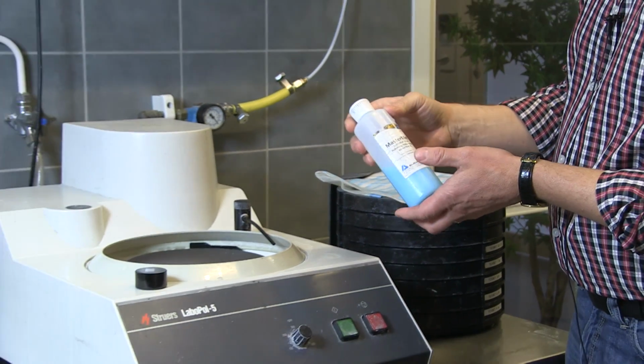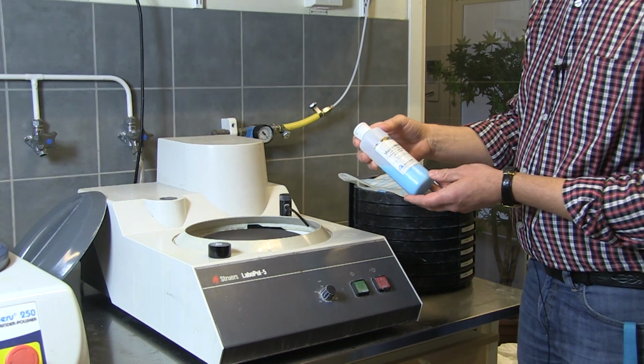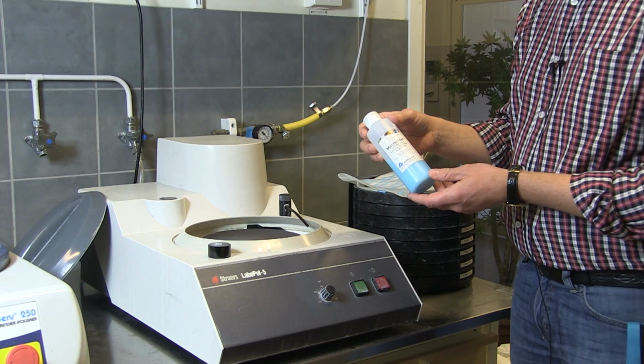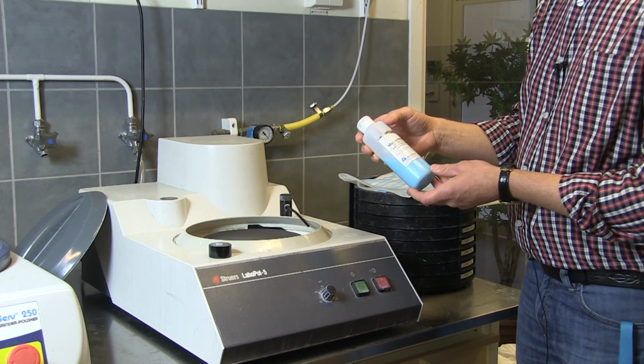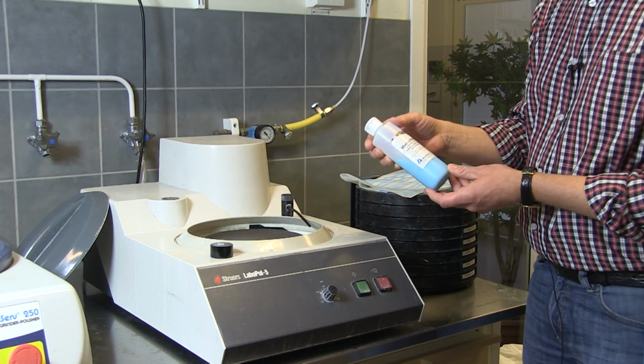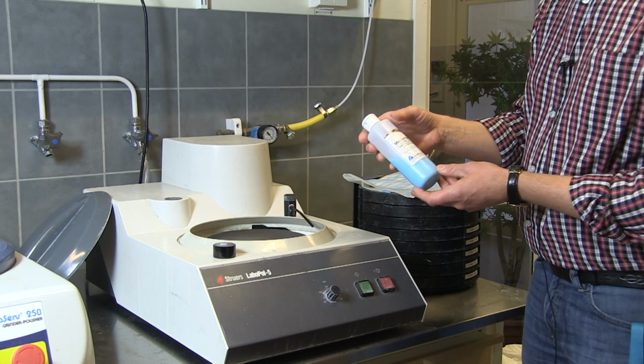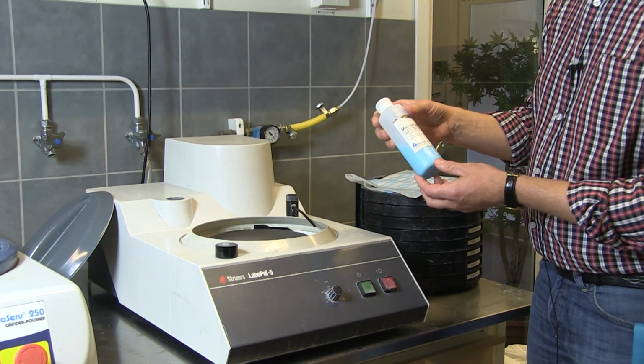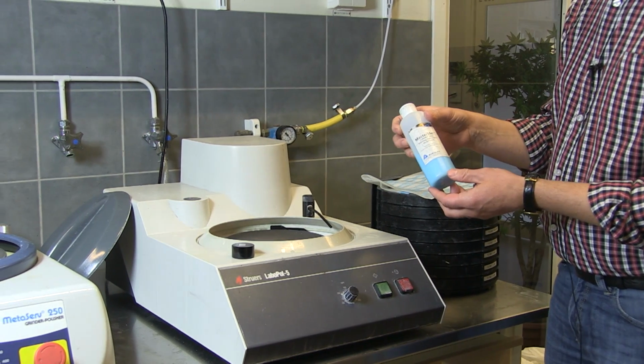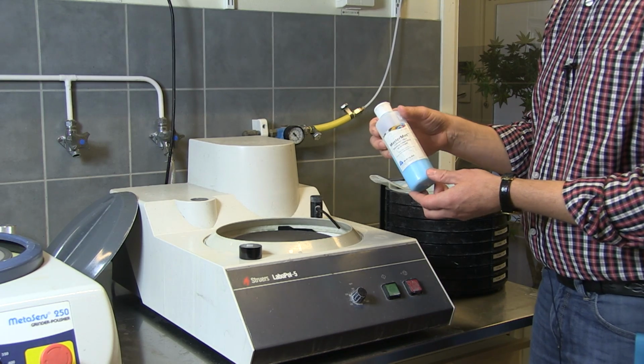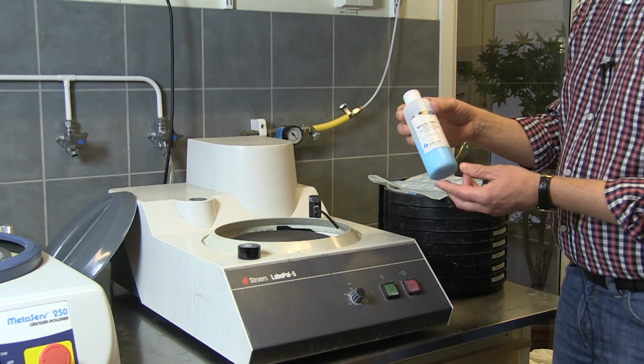Colloidal silica, silicon dioxide. The particle size is 0.06 micrometers, so it's very, very much smaller than 3 micron. But the number of particles is very high. They are also very, very sharp, so they remove a lot of material per time unit. So we will use that one.